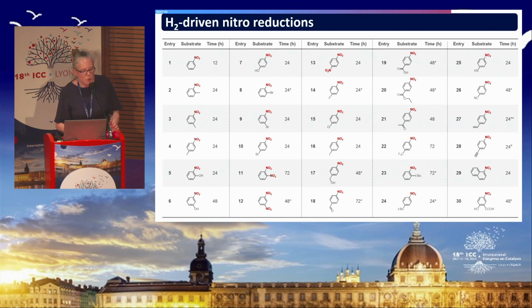And so we've shown that this works on a wide range of different nitro compounds, and I'll just pull out a couple of examples of why we've picked certain functional groups here. We've done this with sulfur containing nitro compounds because those often poison a palladium catalyst and hence cause problems using conventional metal catalysts. We've done this on molecules that have other unsaturated functional groups like alkynes, ketones, carboxylic acids, alkenes, and all of those selectively reduce the nitro compound without touching the other functional groups there.